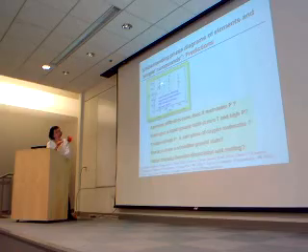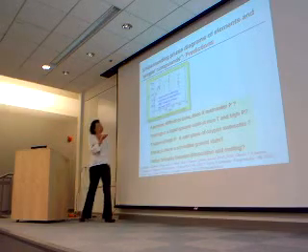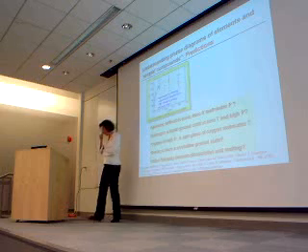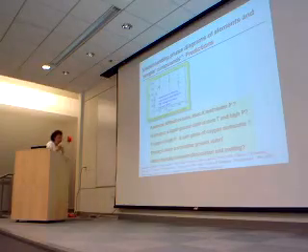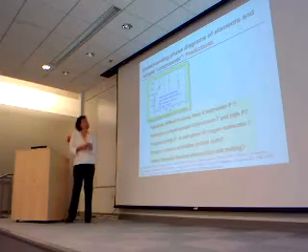A prediction was made, in particular in this case about the fact that there is a maximum in the melting line of hydrogen, and the experiment confirming the existence of this maximum was done later on. It was done in Silvera's group at Harvard a couple of years after the simulation. And it's a nice example of a simulation that has predicted a phenomenon that then has indeed been verified experimentally.